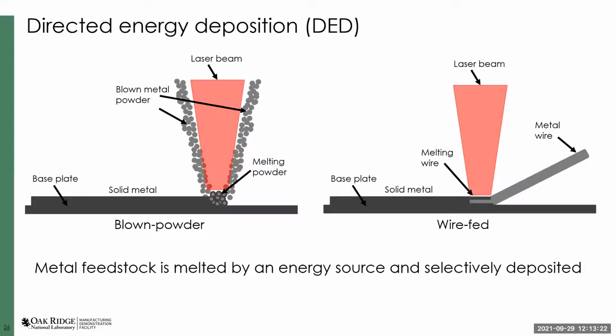There's also wire-fed DED, as you can see in this other image, where you basically take a wire and feed it in instead of blown powder. Blown powder is particularly exciting because it enables things like functionally graded materials, so you can change powder composition on the fly, which is pretty exciting. I mean, you can shift from one material to another in a single component.